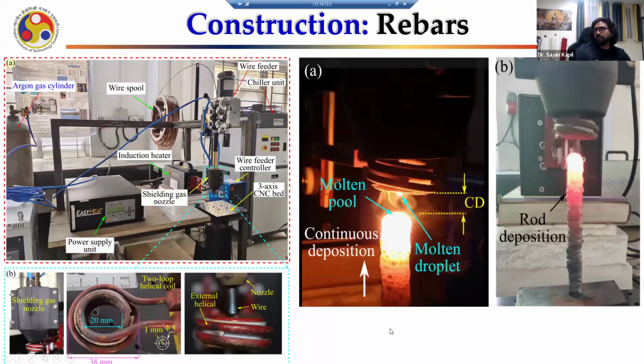This is an interesting 3D printing, again a DED process, but not with welding, with induction heating. Here, the induction heater is generating the heat, partially melting the deposition, as well as depositing the new bead. We are also working right now on putting some permanent magnets in a way that it directs the induction heating, I mean, the magnetic lines, towards the substrate, so it locally melts the substrate also.